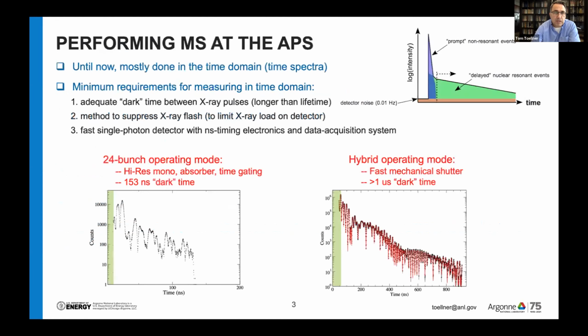So the way we do it currently is in the time domain, up till now, with the small exception that the fast shuttle spectrometer can do both time domain and energy domain. Almost all of our Mossbauer spectra are taken in the time domain. This involves an X-ray flash that excites all the nuclear transitions in a sample, allows them to interfere, and then the manner in which they decay is reflected in the time response. And from that, one can extract the hyperfine interactions in the sample.